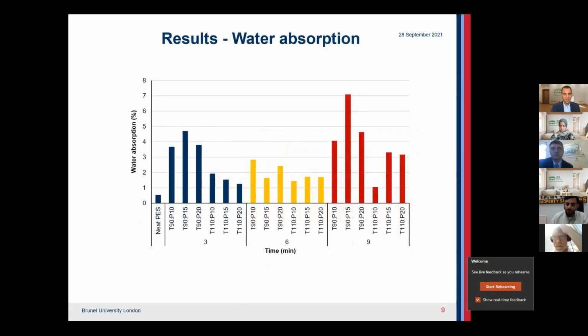Figure 2 shows the water absorption. Also, as the time increases, the water absorption of the composite also increases. However, there are some results that show that there is a certain parameter that shows a minimal increase, or a certain parameter or combination of parameters have the best ratio.